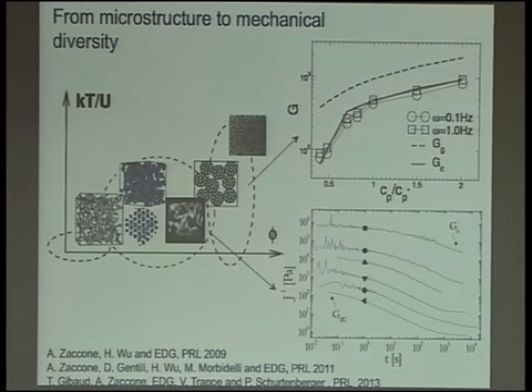And so with the simple modeling, we have been able to show that in fact these two distinct moduli, you can directly connect them to the feature of this complicated bicontinuous network, because it can be associated to the stretching and the bending modes of the thick branches of the network that can develop over quite different time scales. I don't want to go into details of this, but this is just a motivation to show that really you can think of inducing a specific type of microstructure to bring in some interesting mechanical properties that were not there at the beginning.